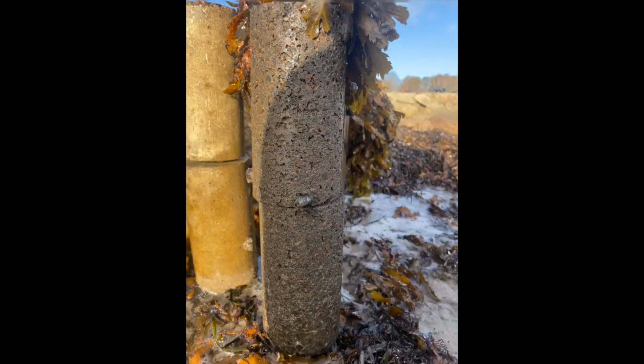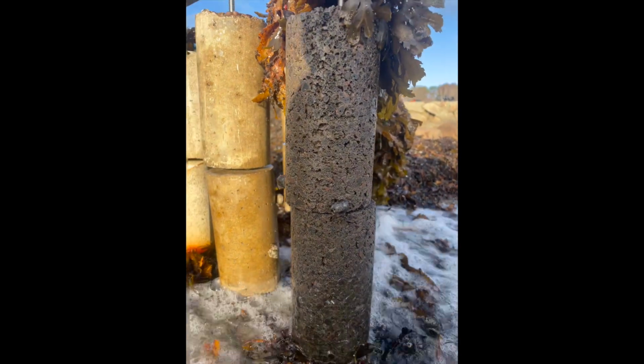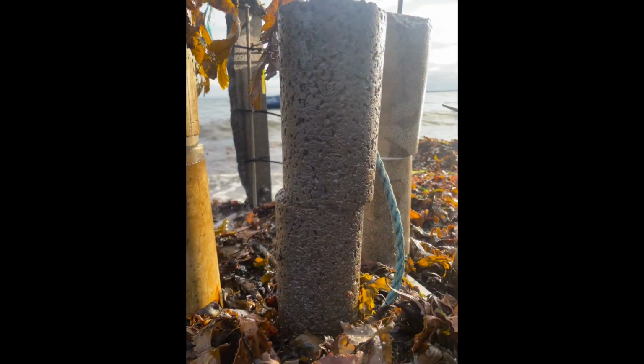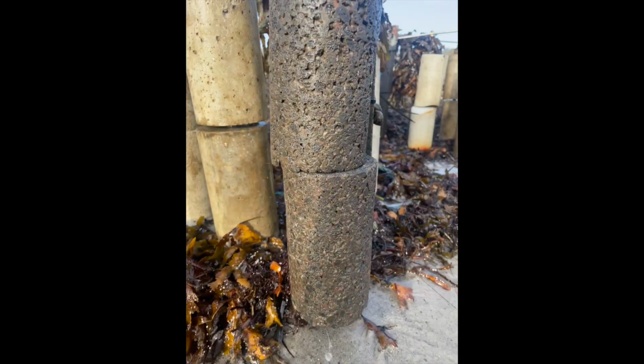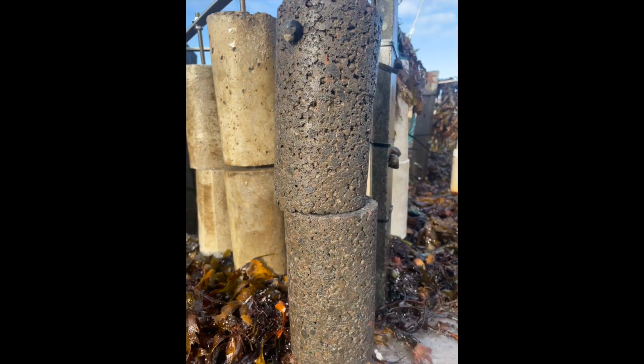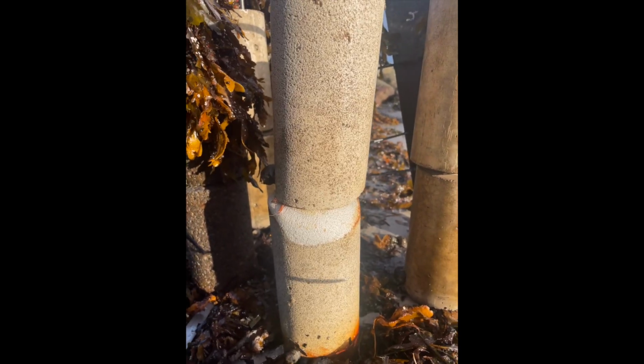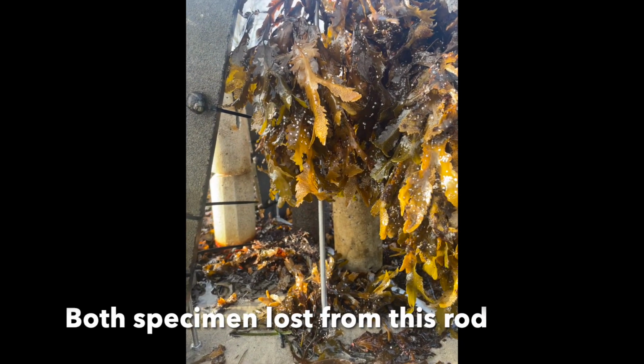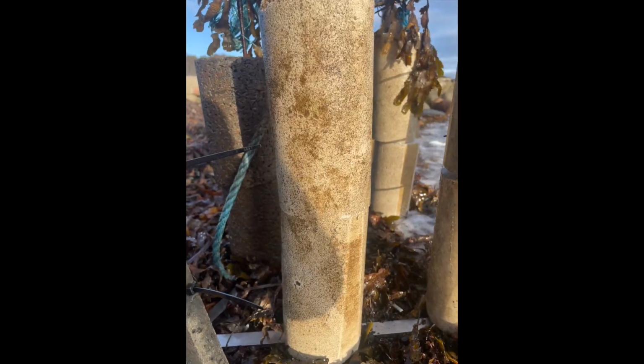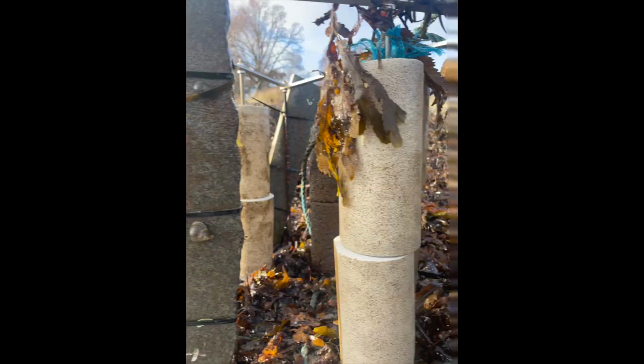The Lytag concrete arguably fared the worst. It had little to no algal growth. This partly disproved porosity as the most important ecological trait for concretes. The AAC seemed to perform the best out of all the materials. The complexity at the surface seemed to retain algae growth better.